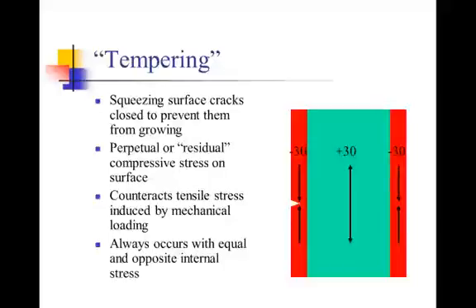And what we do is we place a stress. I have a negative here to show that it's a compressive stress, and that is squeezing this crack on the surface closed. And that's going to be all over the surface of the material. And just like a magnet, when you have a north pole, you have to have a south pole. When you place a compressive stress on the surface of a ceramic, the interior develops a tensile stress. So you actually increase the stress in the center of the ceramic material. It turns out that this is usually not a problem, and here is why.